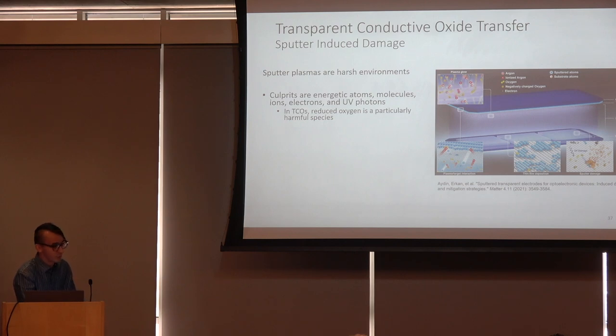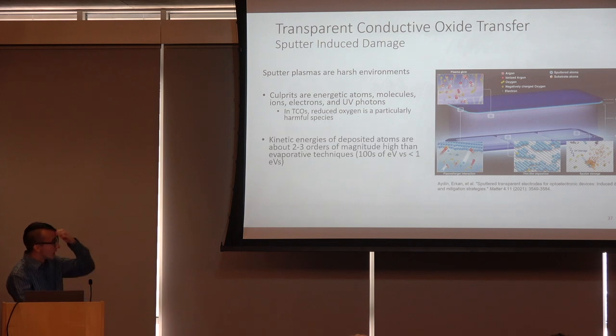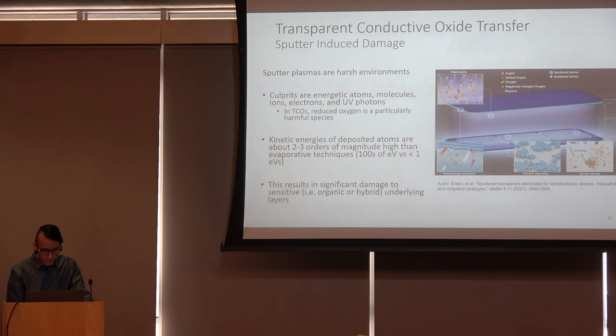Some of the culprits would be energetic atoms, molecules, ions, electrons, UV photons. In the case of TCOs, reduced oxygen is particularly harmful. And the kinetic energies of the particles in these plasmas is 2 to 3 orders of magnitude higher than what you see in evaporative techniques. Hundreds of electron volts versus less than 1 electron volt. This results in very significant damage potentially to your substrate, especially if you have some exposed sensitive material.